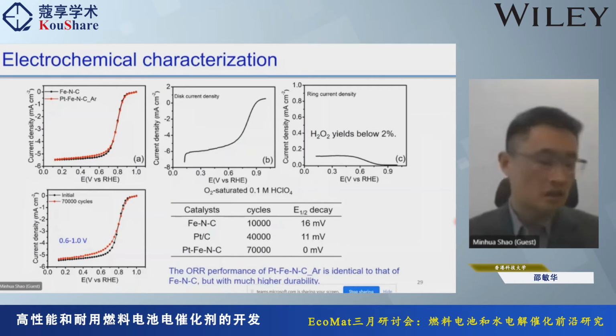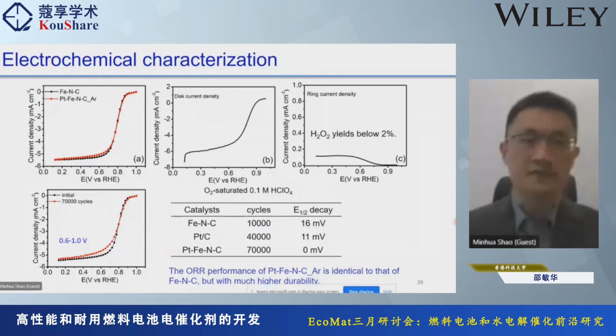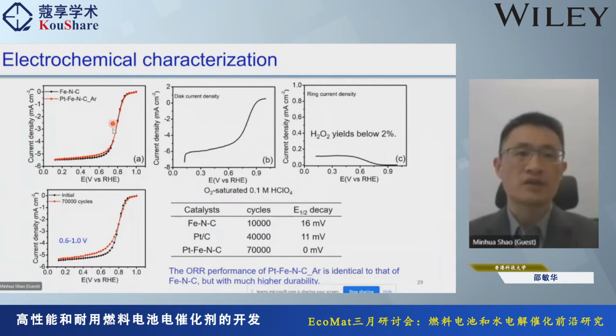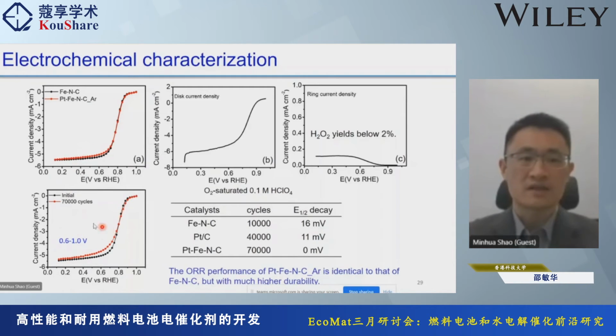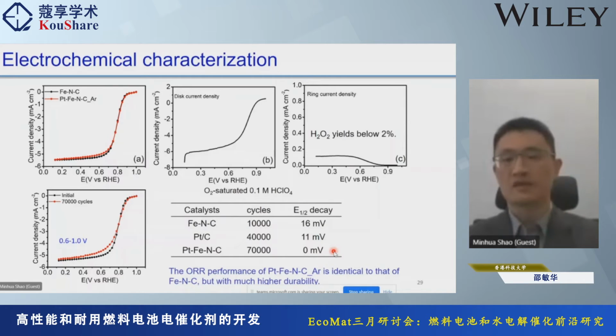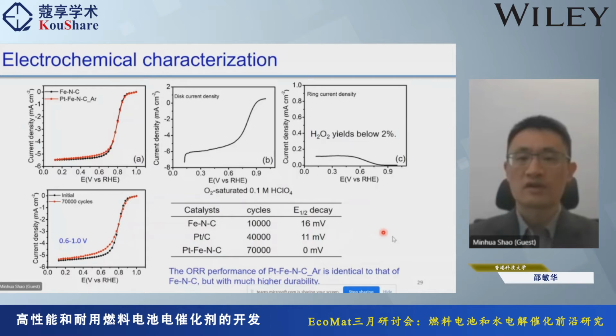And we did some testing, and you can see that in the RDE testing, the iron nitrogen and the platinum doped iron nitrogen basically show no big activity difference. But surprisingly, you can see that if we do the cycling after 70,000 cycles, the activity of the platinum iron nitrogen does not show any activity decay. Okay, so there's no difference in the half-wave potential. But for the iron nitrogen, it's only 10,000 cycles and 16 millivolt, and for platinum, 40,000 cycles and already 11 millivolt.